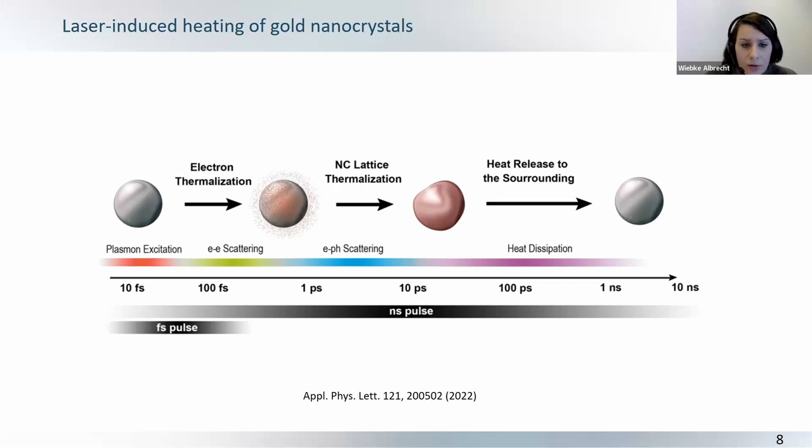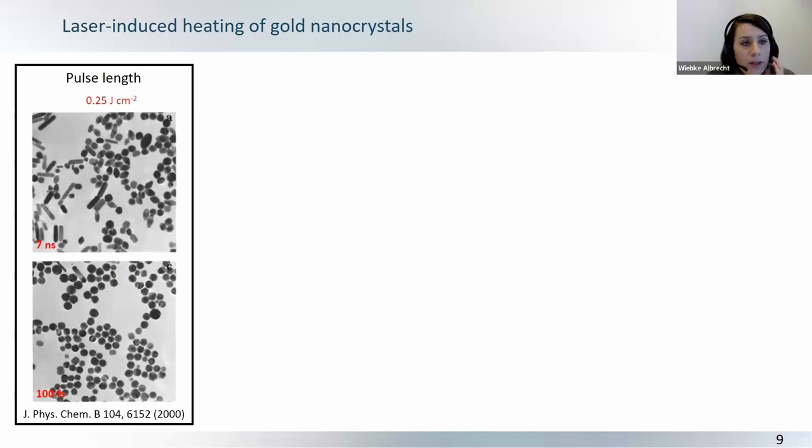This has been also shown experimentally, where people looked at what are some of the parameters that influence these reshaping mechanisms, and the pulse length is a very critical factor. This is some of the earlier work from Stefan Link, where he looked at nanosecond versus femtosecond excitation. And because with nanosecond excitation, you compete with cooling, you basically always need higher pulse energies to achieve similar kind of deformations.